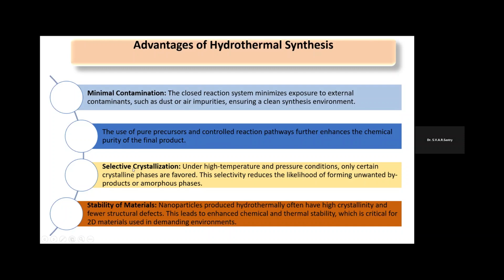Then we also have selective crystallization. Under high temperature and pressure conditions, only certain crystalline phases are favored. This selectivity reduces the likelihood of forming unwanted byproducts or amorphous phases. As we saw before, with temperature and pressure as parameters, high temperature and high pressure give crystalline nanoparticle formation, and lower temperature and lower pressure give amorphous nanoparticle formation.